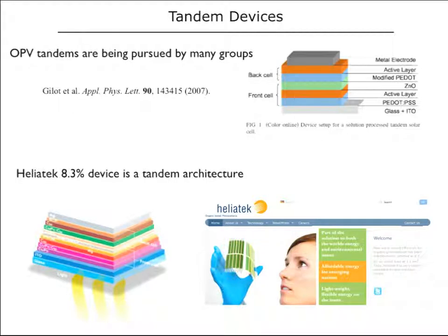Okay. So beyond the single junction, of course, we want to work on tandem devices. And a tandem device for organic photovoltaics is a complete no-brainer. We have the advantage of easy processing of the materials. We can solution deposit. We can vacuum deposit. There's an additional benefit of organic materials, which is that the absorption spectra are relatively narrow bandwidth. So in fact, it does not matter the order in which we put the bands. We can put the low band gap component on the bottom or on the top, and it'll get absorbed. Light will get absorbed as is needed throughout the device.